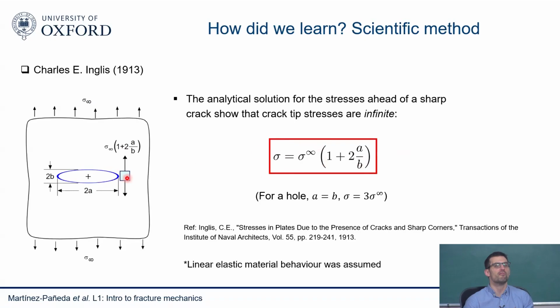If the stresses are infinite near my crack, then if I apply a tiny load, and I assume that things are going to fail due to the stress reaching a critical quantity, everything will fail. Because no matter what, defects are always there, they might be larger or smaller, but that defect is going to grow, because if the growth criterion depends on the stress reaching a critical value, then a tiny applied load will reach that value just because the defect is sharp. So that was puzzling. And of course, there are a lot of ifs here.